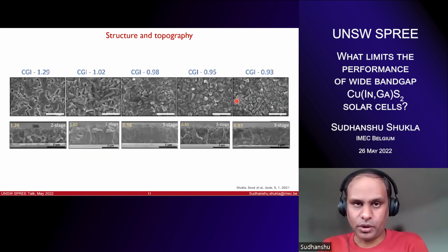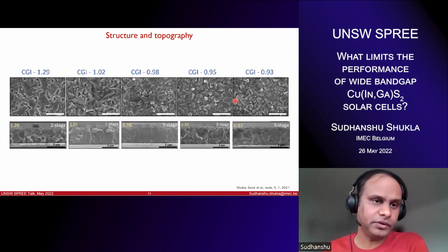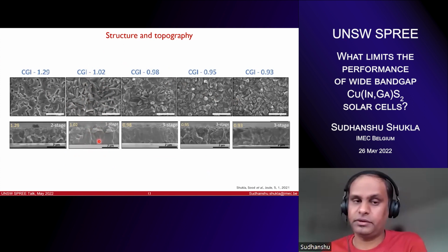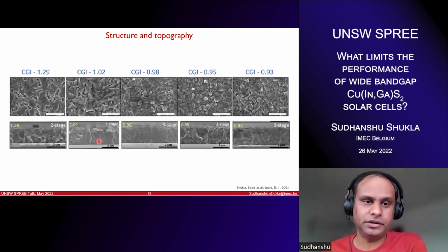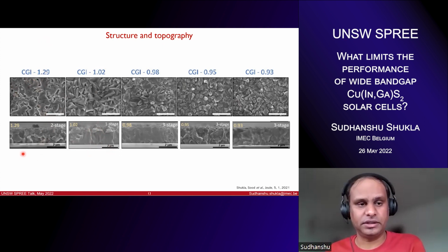So this is the topography of the film. Pretty expected, if you look at the stoichiometric composition, it looks quite rough. At the same time, you have these deep trenches. That's why when we wanted to make solar cells out of it, the cells were mostly shunted because of this bad morphology. For the copper rich films, we anticipated better grain growth. As you can see, the grains are bigger in the case of copper rich.